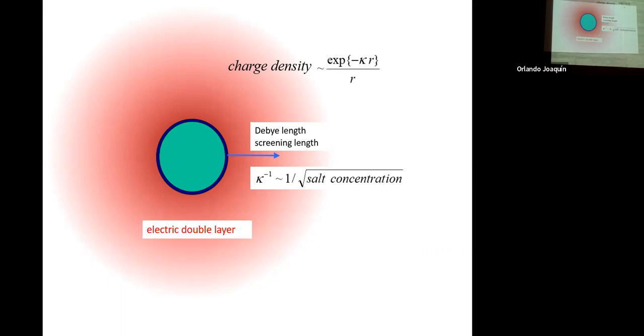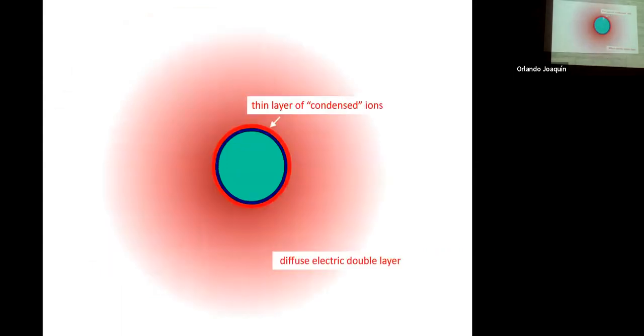You have an additional phenomenon called ion condensation. If the surface potential is very high, you'll also have a layer of condensed ions, where the concentration of positive ions is very large, and this is a relatively thin layer. So we have two types of distributions around the colloid surface: a positively charged thin layer with high charge density for the condensed ions, and this diffuse electric double layer, whose extent decreases with increasing salt concentration.